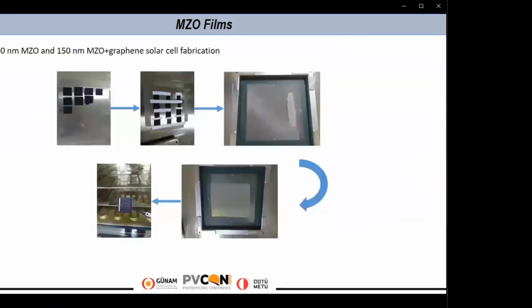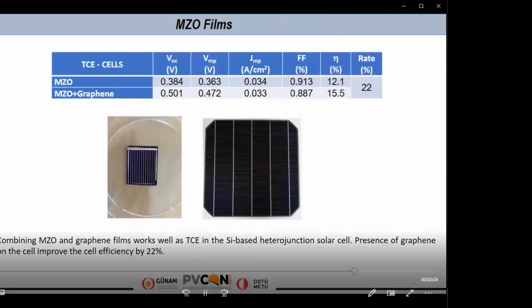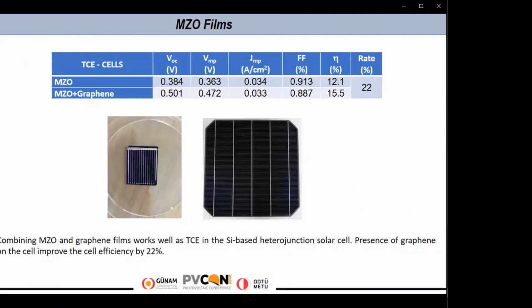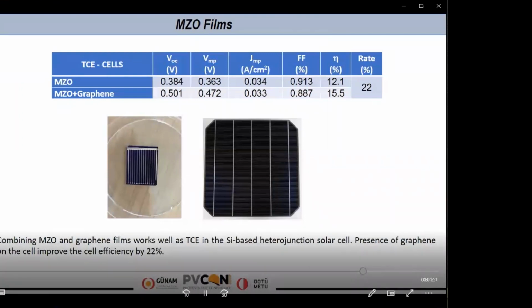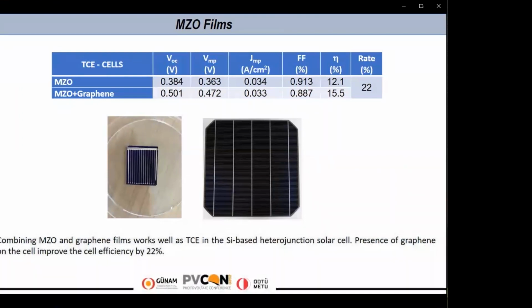1-inch MZO and hybrid solar cells were fabricated, then cell efficiency was measured by solar simulator. So the MZO and hybrid solar cell efficiencies were compared with each other. At this point, when we investigate them, the MZO solar cell has 12% efficiency, and the hybrid solar cell has 15.5% efficiency. Solar cell efficiency was increased by graphene.